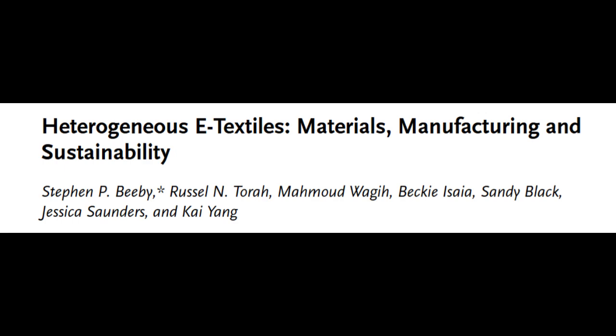Any breakthroughs with inkjet inks mentioned? Yes, a significant development highlighted is the use of particle-free reactive silver inks. Particle-free. I thought conductive inks use tiny metal particles. Many do, and that can cause problems like nozzle clogging and maybe imperfect bonding between particles and to the fibers. These reactive inks are different. They contain silver compounds dissolved in the ink. When printed and cured, the silver compounds react and deposit silver atoms directly onto the fibers, forming a continuous, highly conductive coating. So it's like plating the fibers in place.